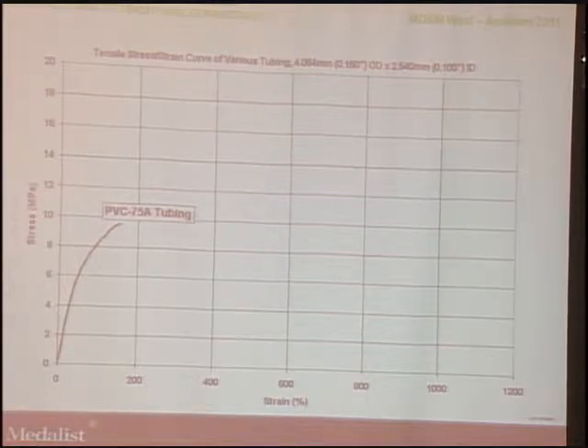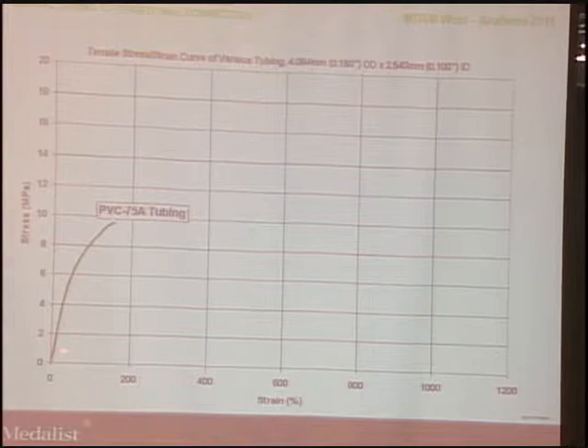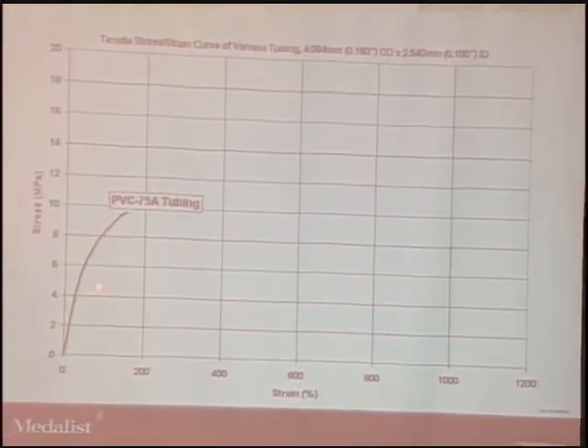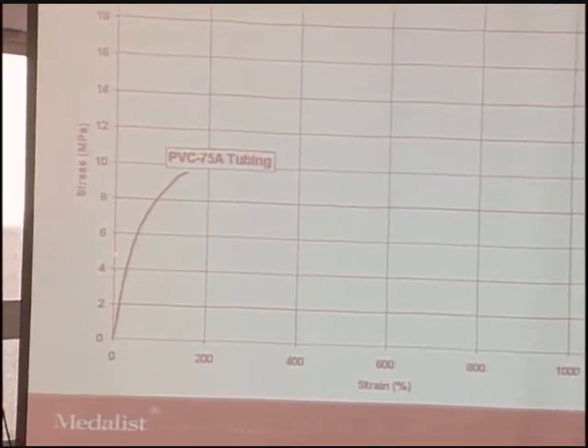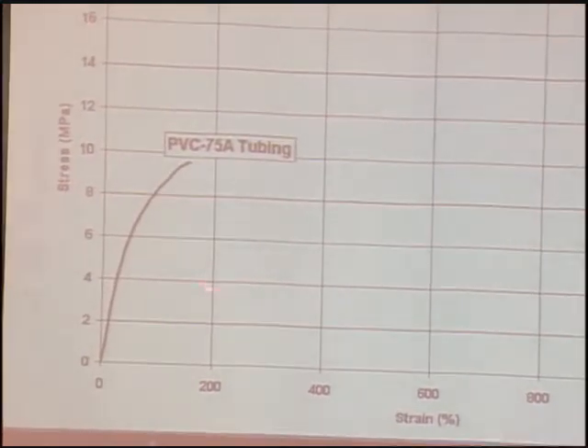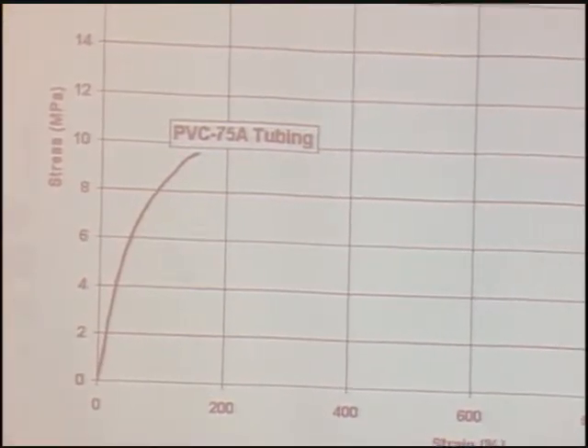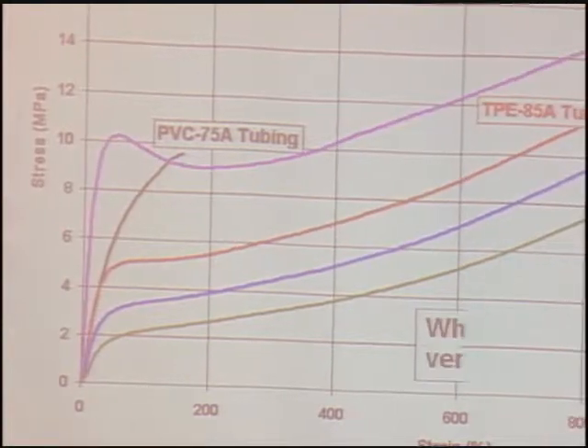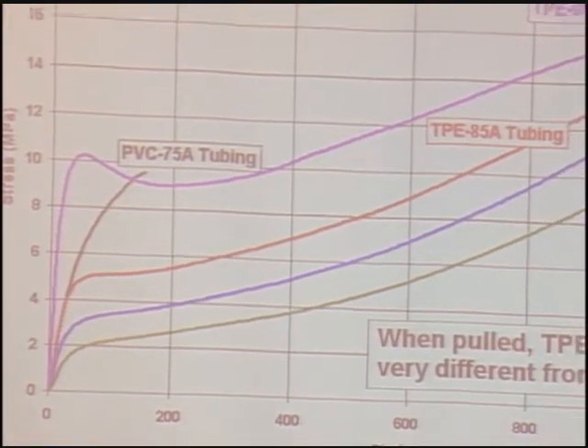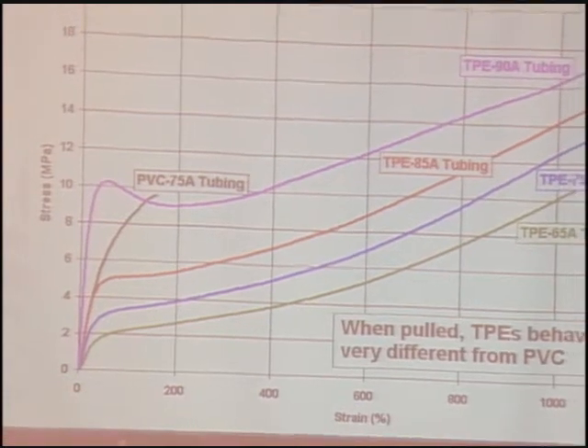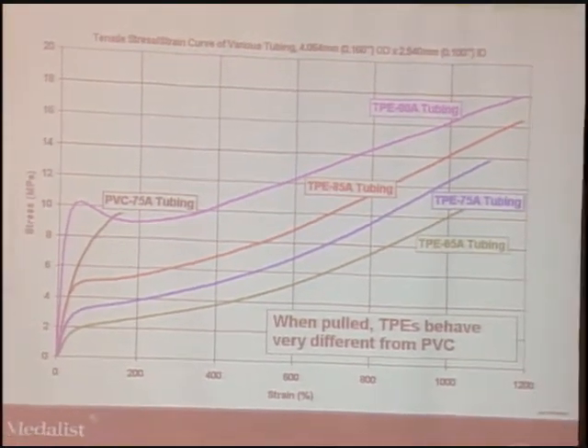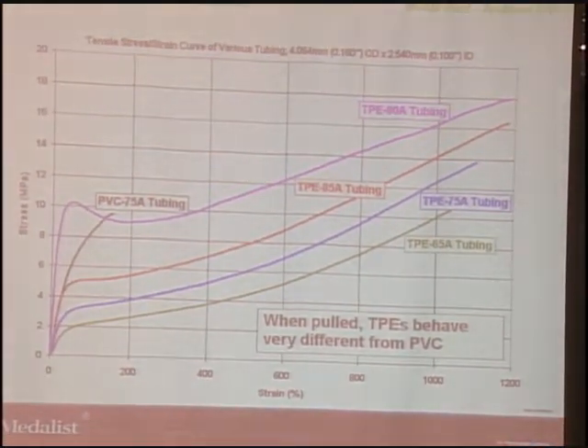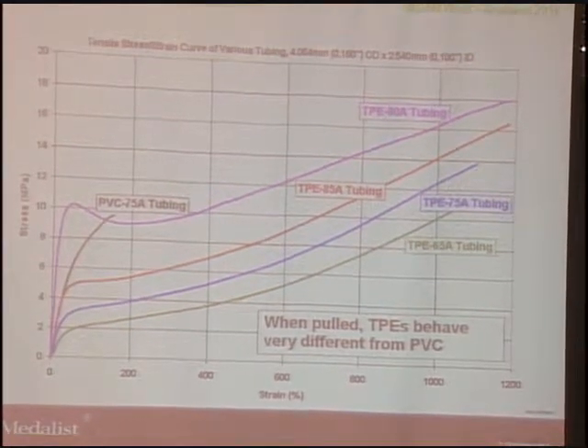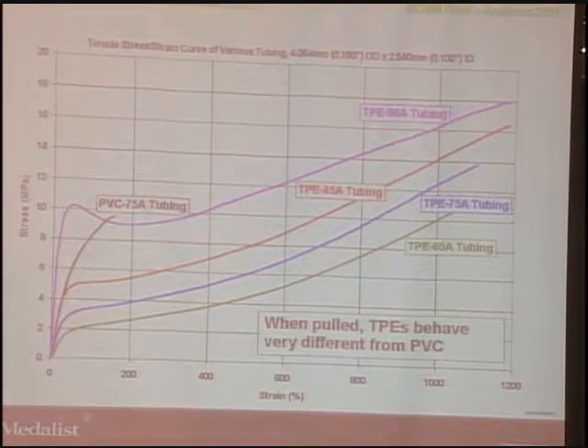Let's compare the tubing. When you pull the tubing of a PVC versus a TPE. For PVC, when you pull the tubing, the stress goes up very quickly. It will break at typically less than 200%. However, for TPE, when it's the same size of tubing, when you pull it, it stretches, and usually won't break until it reaches more than 10 times its original length. So it really stretches.